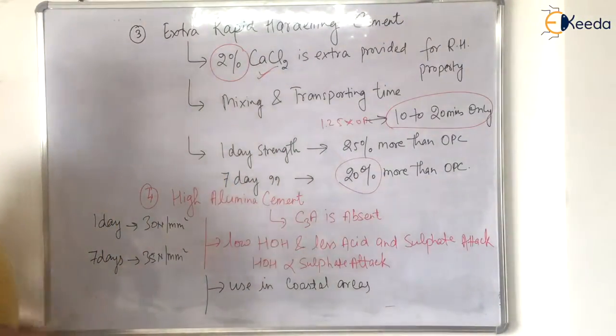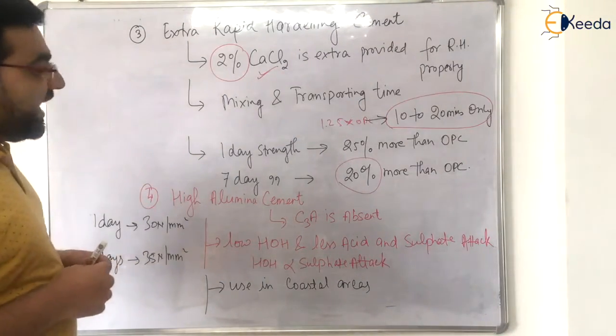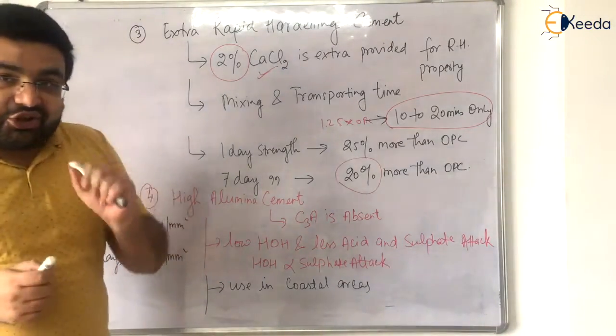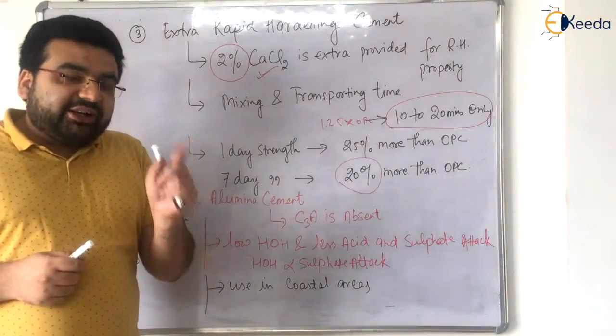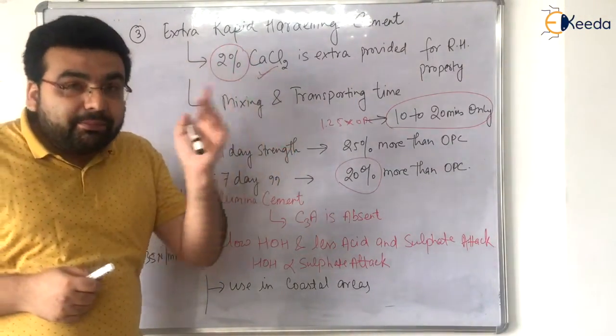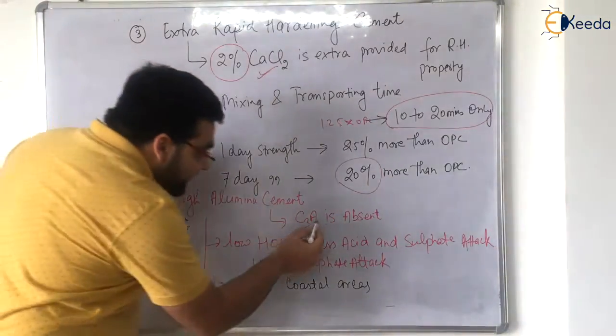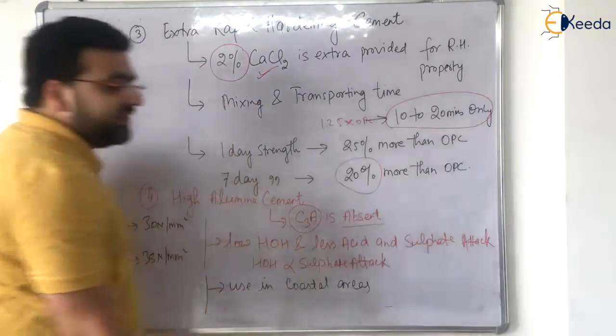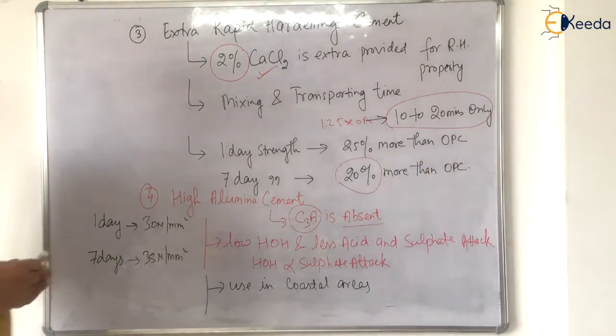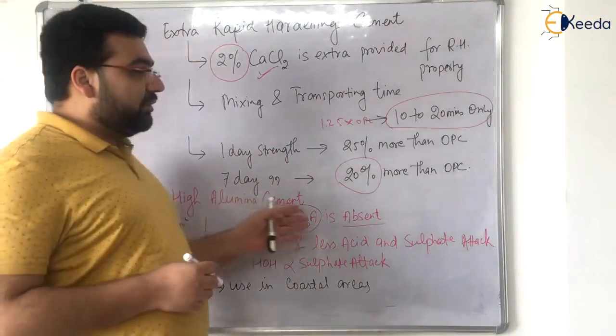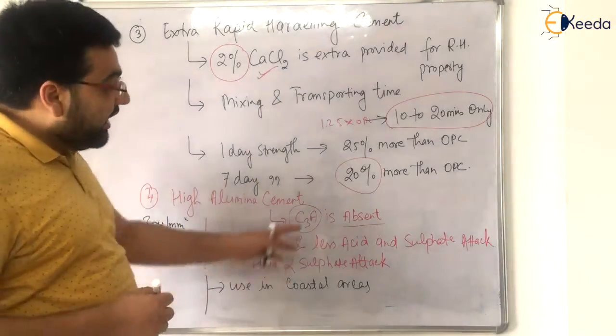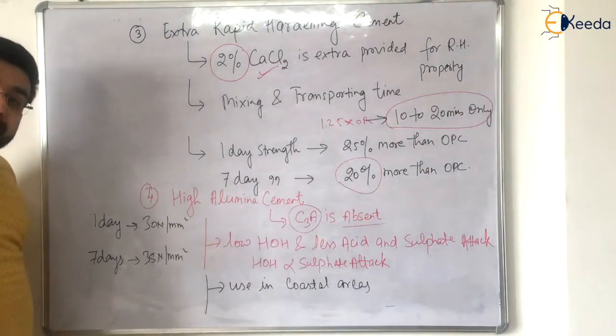Okay. Now the next type of cement is high alumina cement. Now, there is a trick, right? The name is high alumina. It means that aluminum content should be higher, but you know that C3A is absent here. This is the trick, okay? So don't get confused. High alumina does not mean it has a very high content of alumina. It means that C3A will be absent, right?